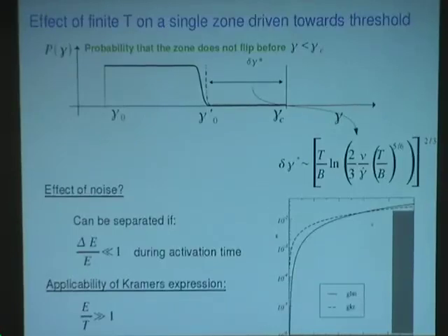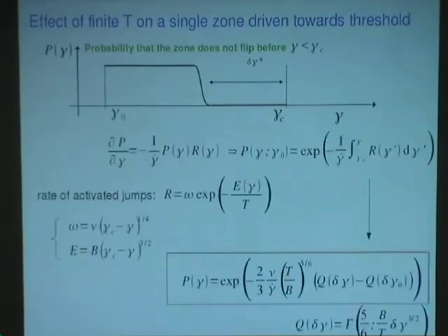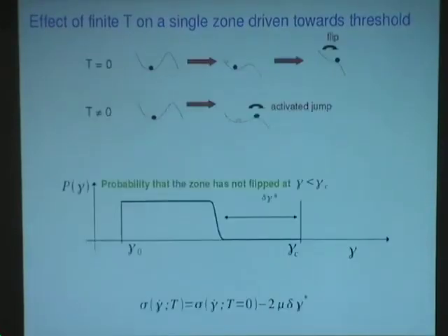No, I think the activation we are talking about here is really an activation. Okay, let me just find these barriers again. What I'm talking about applies only if you're far enough from the barrier state, because the activation will be really at work in significant anticipation of the plastic event. And so what controls this is really the vibration along the unstable direction, right? And so it's really elasticity at the scale of your particle which controls that.